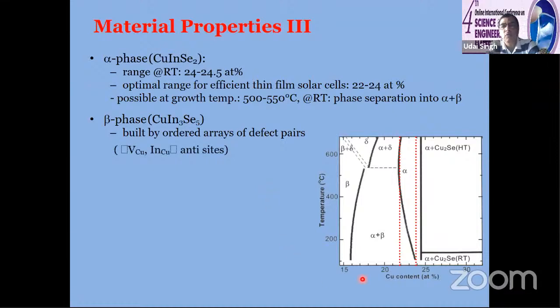What problem comes, if you see the phase diagram. This alpha phase is the pure copper indium diselenide phase. The band is very narrow. You have to maintain copper between 22 to 24 atomic percent. If it goes above 24%, then you form the copper selenide phase, which is highly conducting. If you go below 22%, then you have the delta or beta phase, these defect states present. So one has to maintain this. That is some of the problem people face during production, like reproducibility problems.